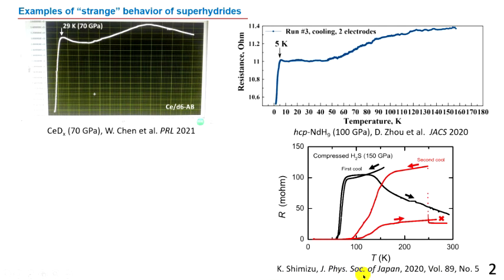And let's see the third picture. I took this picture from the publication of Katsuya Shimizu in the Journal of the Physical Society of Japan, 2020, and we can look at the black curve. It's compressed H2S at 150 GPa, and we see that during the heating cycle, the behavior of resistance of this H2S is not typical for a metal, because the resistance decreases with increasing temperature. It's a typical behavior for semiconductors, but not for metals.